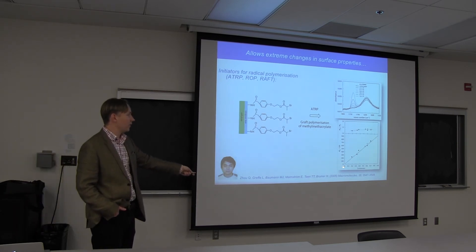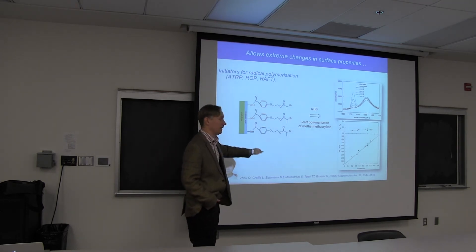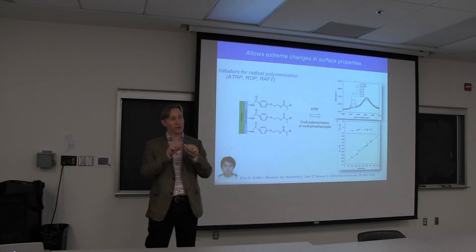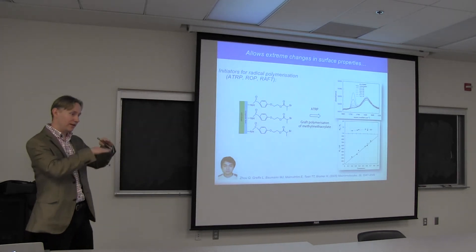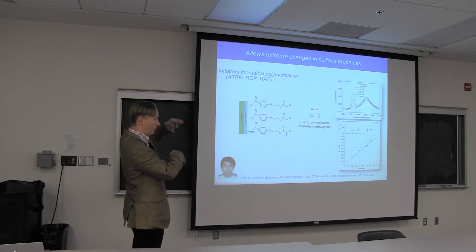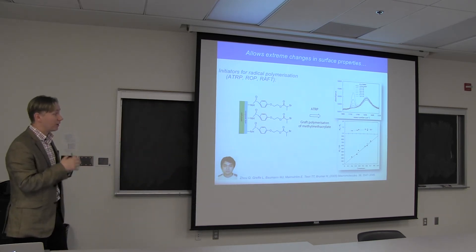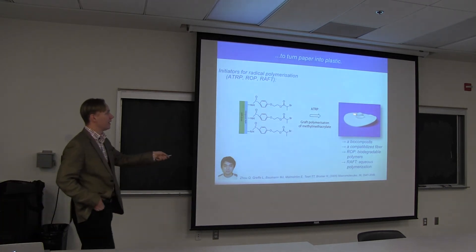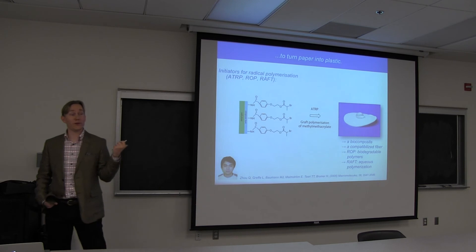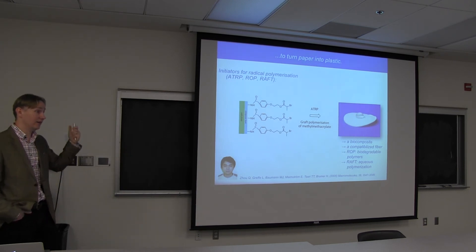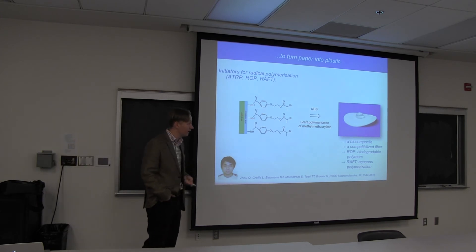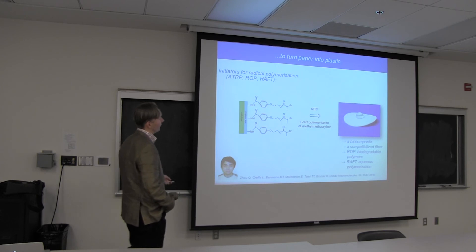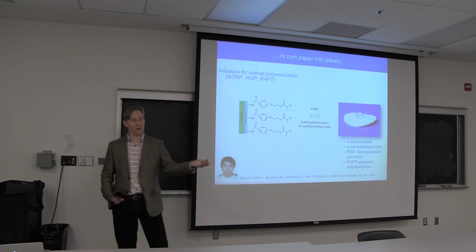We can attach functional groups to cellulose without modifying cellulose at all. We can do this binding chemistry in aqueous solution. We can transfer these over to ATRP conditions and grow polymers off the surface. For polymerizing methyl methacrylate, we can watch the increase in absorbance of the carbonyl group with conversion. We can show the molecular weight increases linearly with conversion. We can show the polydispersity is very low. On a paper sheet, controlled polymerization doesn't make so much difference. But if we're thinking about cellulose nanostructures, to control polymer length, to grow all these polymers at the same rate constantly throughout the polymerization, can be really useful for tailoring molecular architectures. At the end of the day, we can make a paper sheet that doesn't filter water anymore. This drop will stand there until it evaporates. We can make surfaces hydrophobic.